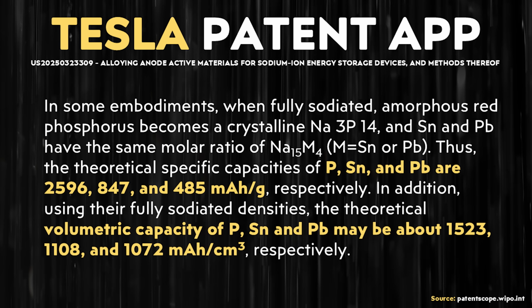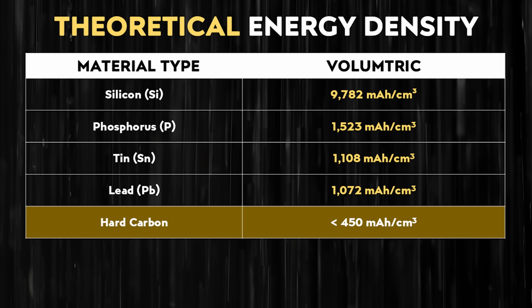of phosphorus, for example, is 1523 milliamp hours per centimeter cubed, tin 1108 milliamp hours per centimeter cubed, and lead 1,072 milliamp hours per centimeter cubed. So when you compare this to hard carbon, which was pointed out earlier in this text, having a theoretical volumetric energy density of less than 450 milliamp hours per centimeter cubed, adding one or more of these alloys should improve the theoretical energy density of the anode of a battery cell.